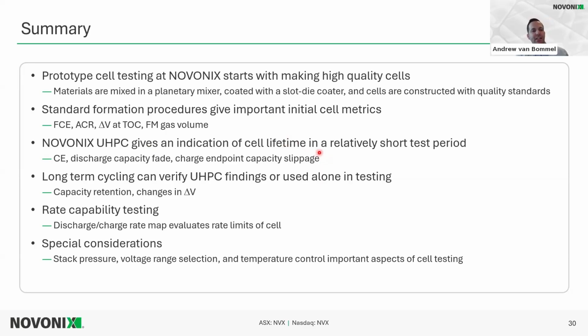And then long-term cycling can verify the findings in UHPC and can also be used alone in testing. As I said, it's important to look at what current and what temperature is used when doing this long-term cycling. Again, 1C at room temperature or 25 degrees might be good to show impedance-based fade, whereas a higher temperature like 40 degrees at C/3 might be better for a time-based fade, to see more degradation at that little bit of an elevated temperature.